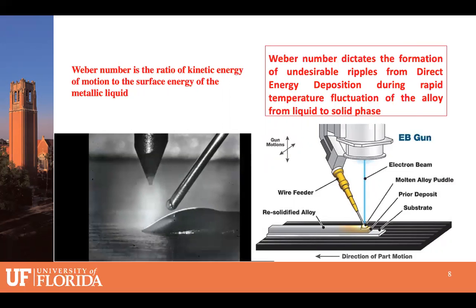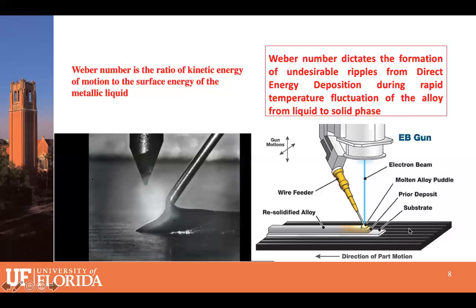Now, as the puddle is being formed, a substrate at the bottom moves back and forth, and this liquid metallic alloy creates a layered deposit that solidifies. An important thing to remember is that you do not wish to have any ripples being formed on this puddle, because these ripples will create a signature on the solidified tool or object and can compromise the mechanical structure of such an object.